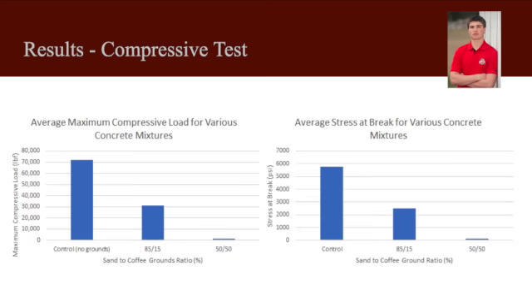Here are a few graphs of the results of the compressive test. Maximum compressive load is shown on the left, while the average stress at break is shown on the right. The control sample took by far the highest compressive load, followed by the 85-15 ratio, and then the 50-50 mix. The 50-50 mix had almost negligible compressive strength compared to the others.